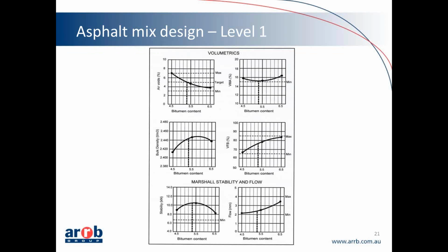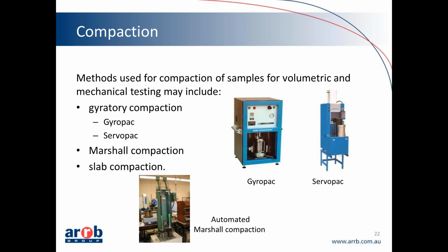Moving to the next slide, sorry, part of level 1 is that it is very important that we prepare samples which are really relevant to in-service conditions. Since the achieved air void content has an enormous impact on the mix performance, in the laboratory design process we compact the asphalt to a density that is representative of the in-service condition. That process or procedure involves the compaction, the conditioning, and the mixing,